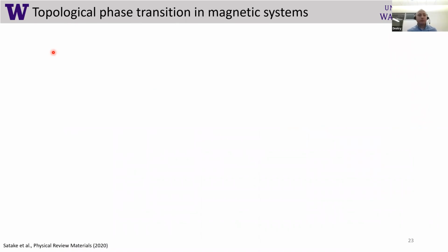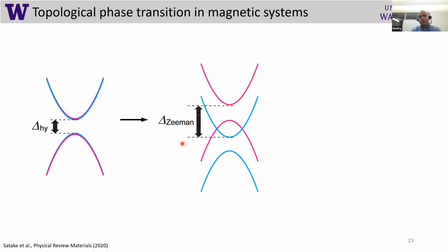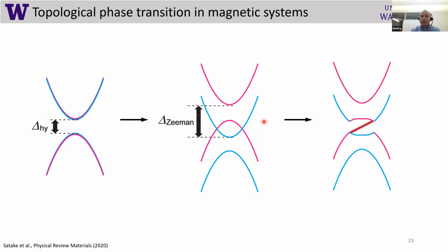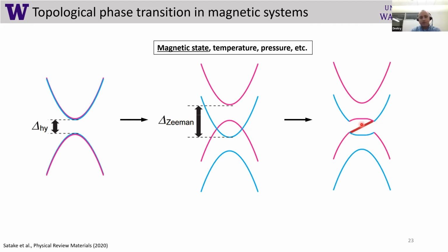Okay, so now let's talk about the results which we got. And the first thing which we were interested in is to understand how topological phase transitions could be engineered in this system. So in magnetic systems in general, for example, you take a non-magnetic system and you introduce magnetism, you essentially introduce the Zeeman splitting in the bands. So in case some of the bands could touch each other and invert, in this case, you get an inverted band structure. And in that inverted band structure, an edge state could reside. So the knob or means to achieve this is essentially magnetic state, temperature, pressure, or other parameters which you could change in your material. And in this particular case, I'll talk about how magnetic state affects the topology of band structure in our material.